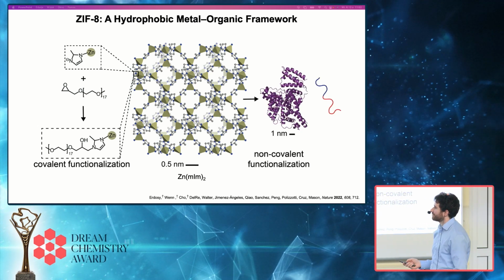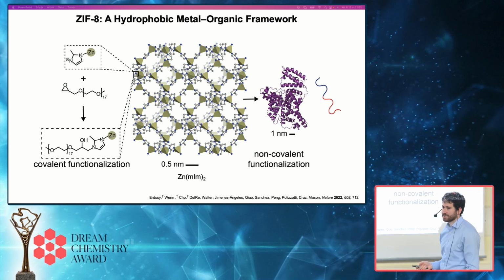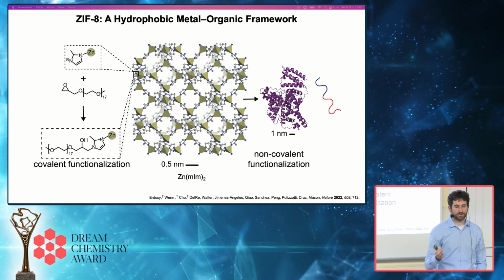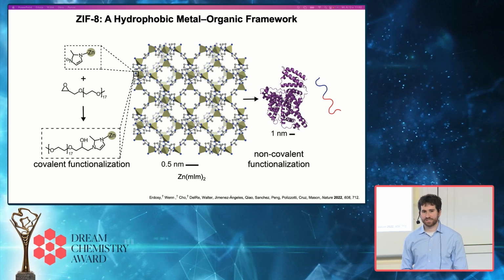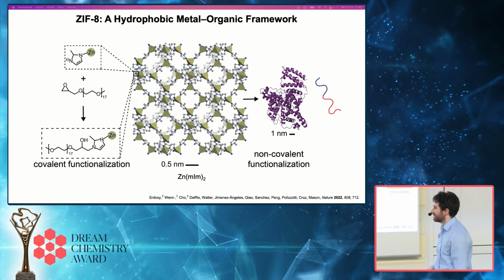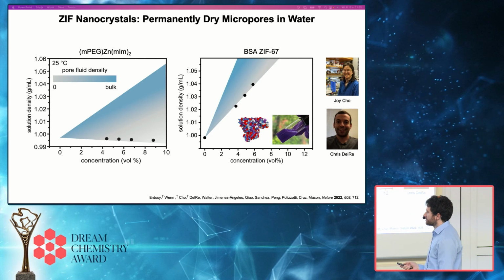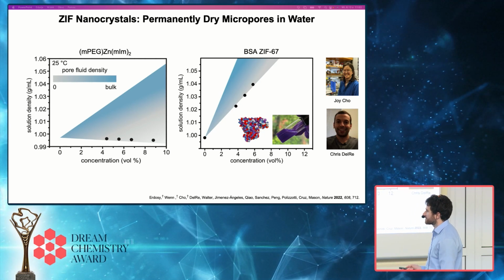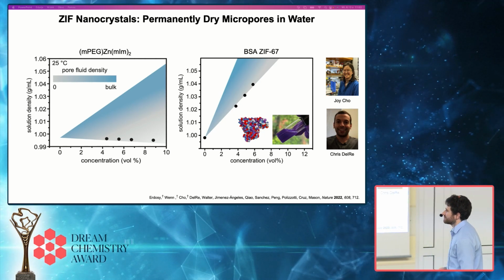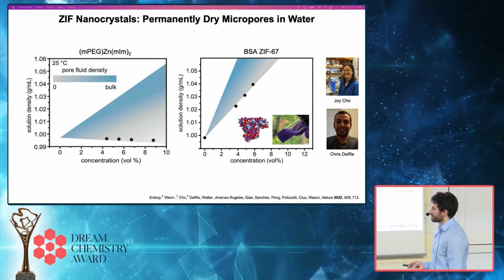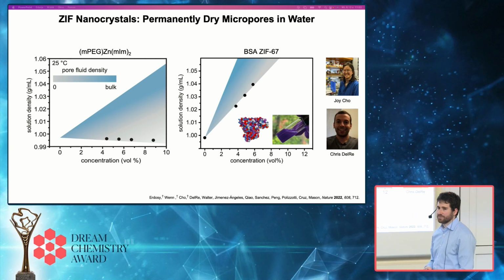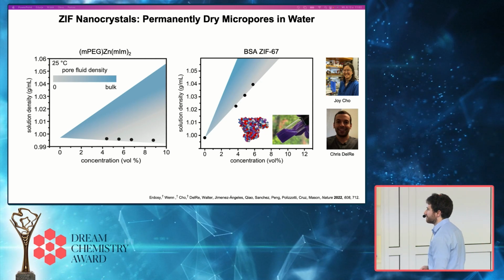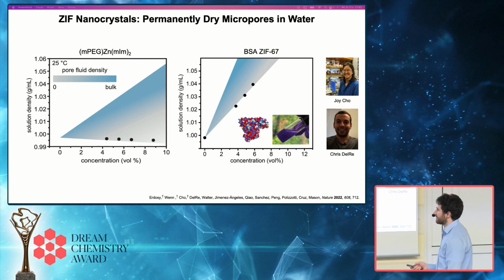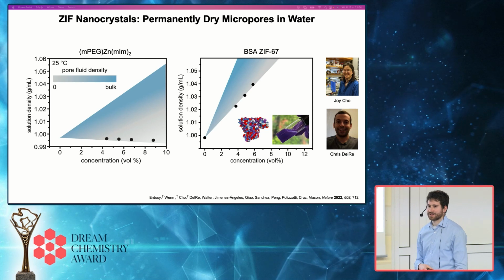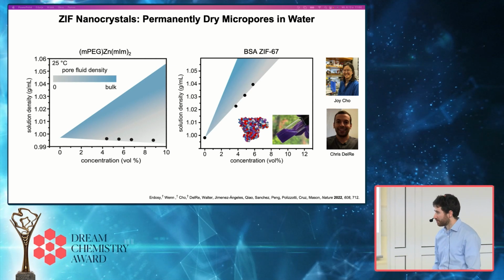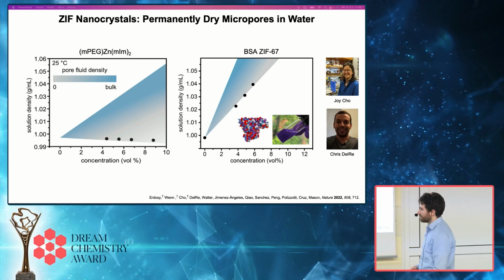We've also spent a lot of time looking at how different proteins and polymers interact with this external surface to try to develop design principles for making these surfaces hydrophilic while still preserving porosity in aqueous environments. And so Joy and a postdoc, Chris, in my group have been able to demonstrate this strategy works for some different MOF nanoparticles where we can make really stable colloidal dispersions of these particles with either covalent or non-covalently functionalized hydrophilic external surfaces that contain completely dry pores that are accessible to gas molecules.